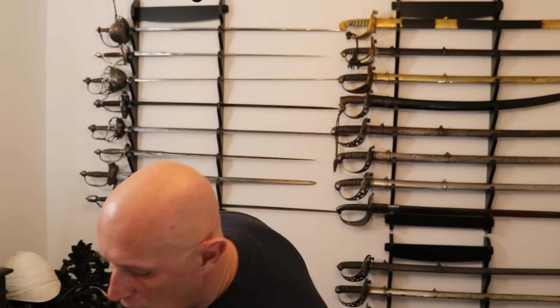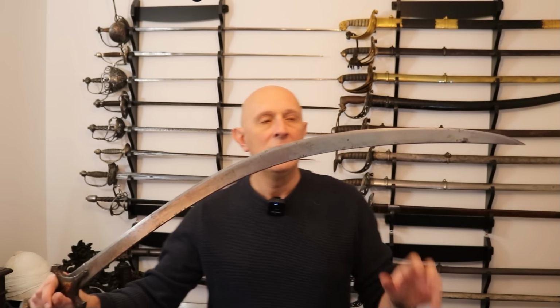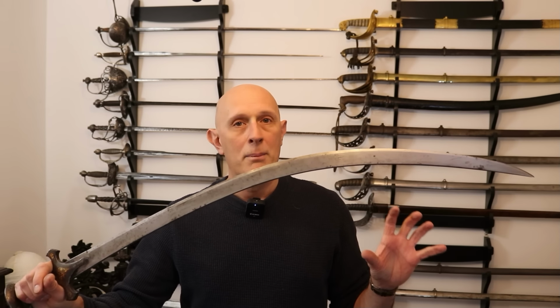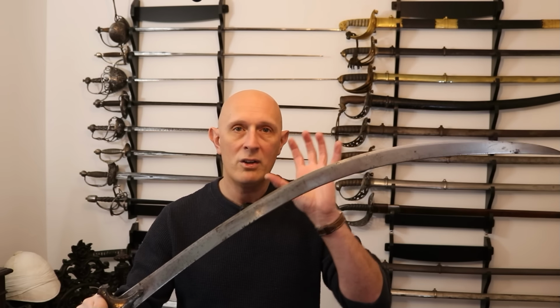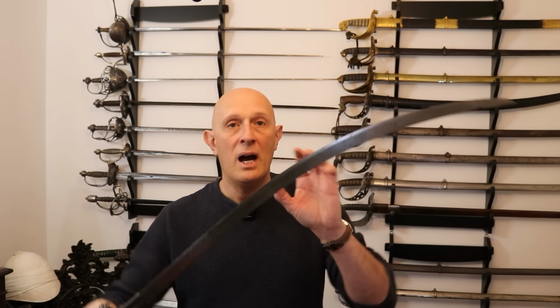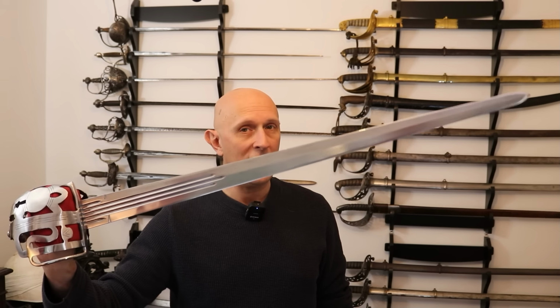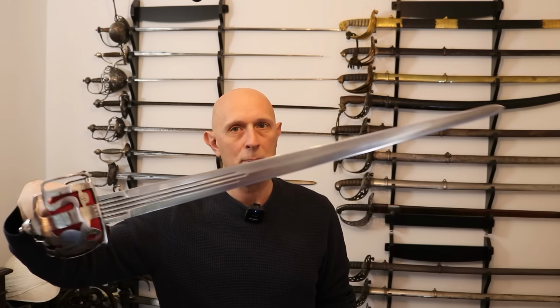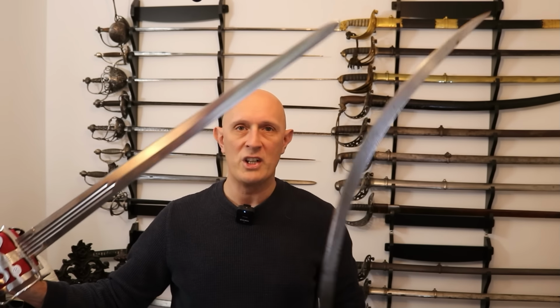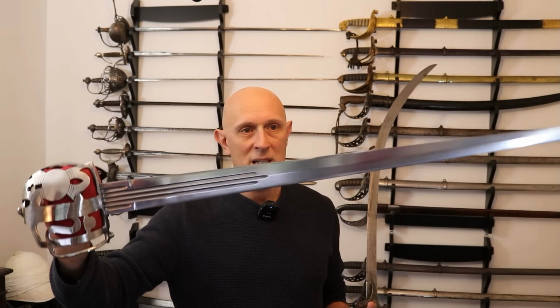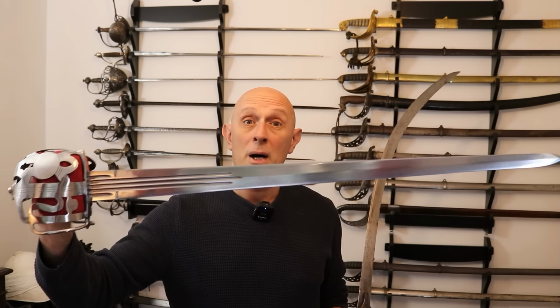So, if you have a Wootz blade, for example, and you try to spring temper this, it will become very brittle and far more likely to break. This can be true of Japanese steel as well, not necessarily, but it depends. So one choice to make is, would you rather have a harder edge and a back which bends, or would you rather have a slightly softer edge with a traditional steel that you're spring tempering, that you might not want to quench as brutally as you could quench an edge on one of these edge hardened blades or a Japanese blade? So a slightly softer edge, but a springy body.